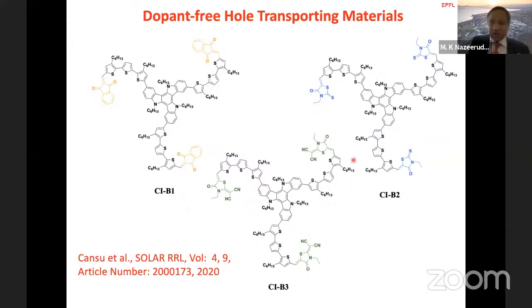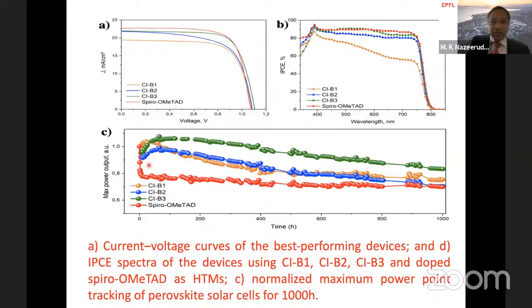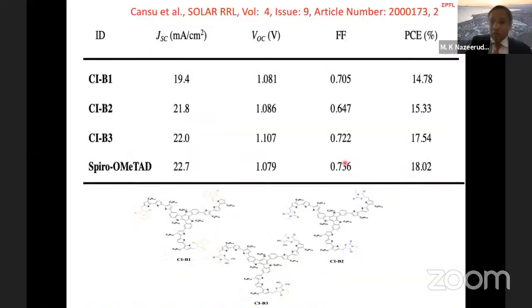These are the three new classes of materials, and they also show very nice efficiencies without dopants, by the way. All these dopant-free hole transport materials are very efficient and comparable to spiro-OMeTAD, as shown here. C1B1 has a 15% efficiency, C1B2 has a 15.3% efficiency, and C1B3 has 17.5%. All these are without dopants. With spiro-OMeTAD with dopants, we have an 18% efficiency.